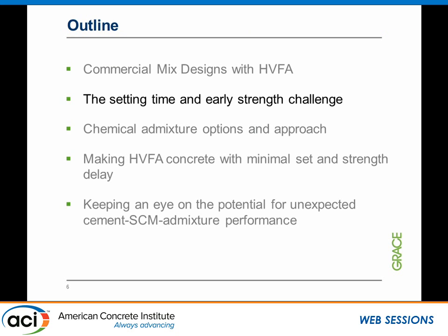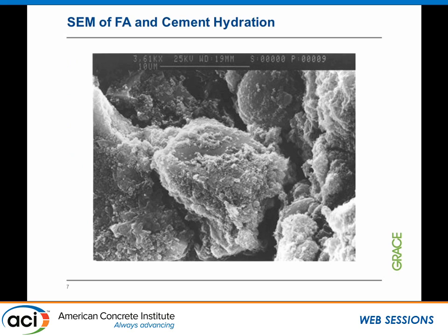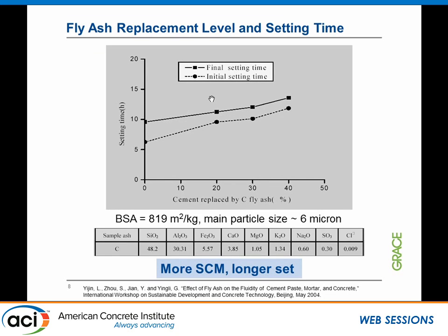So in terms of the challenges of setting time and early strength, many of you have looked at the picture of the SEM where we are looking at the cement particle versus the fly ash particle. This is a one-day picture where you see a lot of hydration products being formed on the cement particles already, but barely much on the fly ash. And therefore, with the addition of fly ash, we don't have the hydration products. Therefore, we get the longer set time and lower strength.